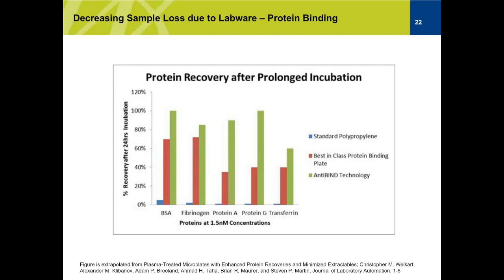What you can see here is that after 24 hours, for BSA and some of these proteins, we lost all of them in the standard polypropylene due to protein adsorption issues, while best-in-class low-protein binding plates give us good recovery. With anti-bind technology, we're able to get 100% recovery for most of the proteins or around that area, and give more recovery than anything that's available out there.